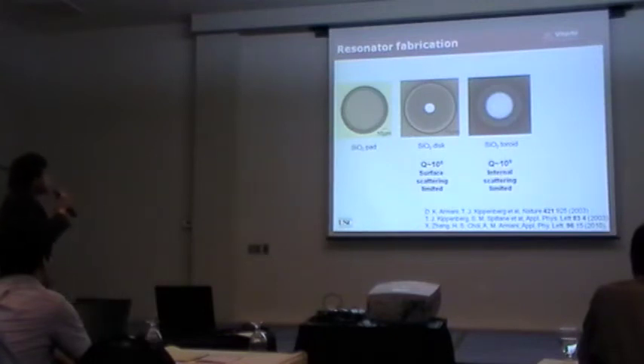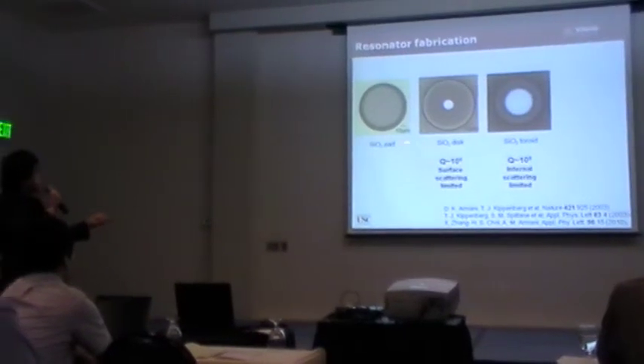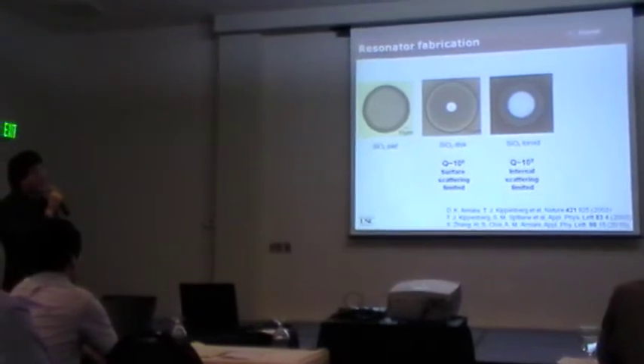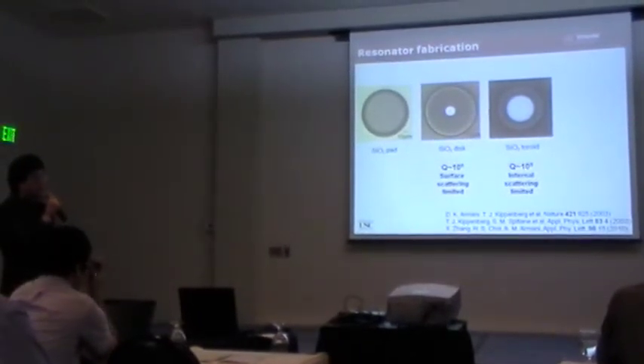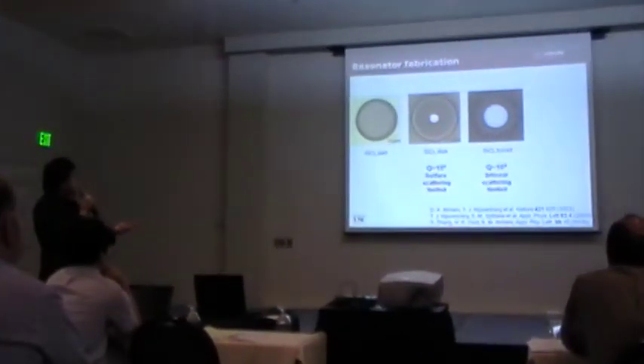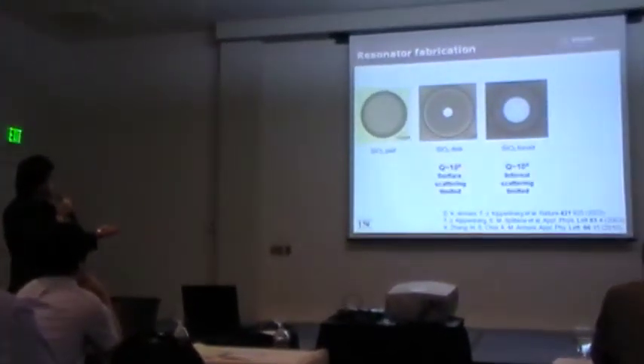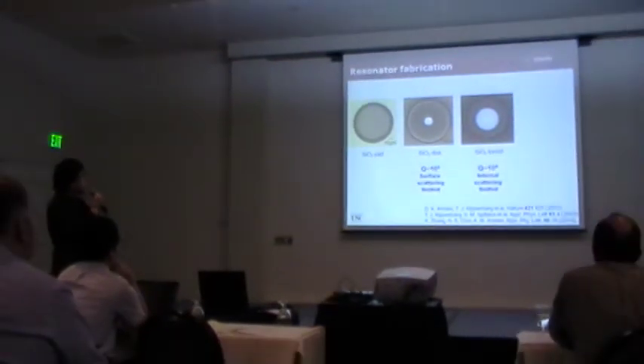To fabricate our devices, we first start with a 2 micron thick oxide layer on a silicon substrate to make the circular pattern by standard photolithography to make the silica pad. Then we use xenon difluoride etcher to selectively etch down the silicon underneath the silica to make a silica microdisc. At this point, quality factor is 10^6, limited by surface scattering. Then we use a carbon dioxide laser to make the silica microtoroid. At this point, quality factor is 10^8, limited by internal scattering.